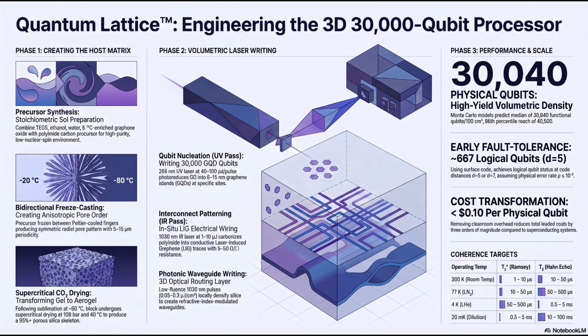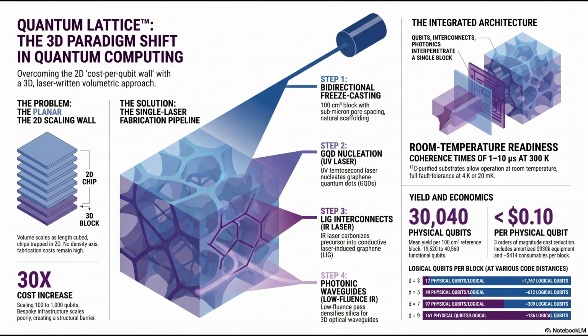Localized melting. So it's essentially squishing the glass structure together slightly. We call it densification. By slightly melting the porous struts, they collapse slightly, increasing the local mass density of the silica along the precise path the laser travels. And in optics, there is a fundamental rule. When you increase the density of a transparent material, you raise its refractive index. The refractive index, that's how much the material bends light, right? Like when you look at a straw in a glass of water and it looks broken. Correct. The paper states this densification process creates a refractive index contrast, a delta N of about 0.01 to 0.1 between the laser scan path and the untouched aerogel around it.